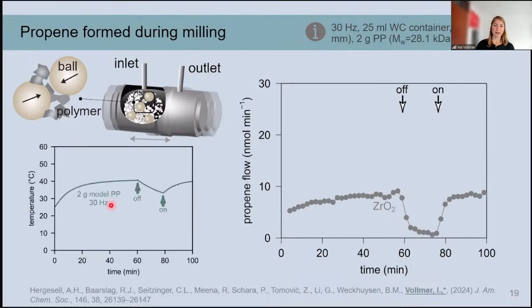And during this same time, we also measured the temperature, and it does increase a little bit because of the friction occurring inside the ball mill. However, when we switch off the shaking, then the temperature actually decreases much more slowly than the propene formation. And this is the first indication that we are not just looking at a thermal effect here, but actually a mechanochemical effect.